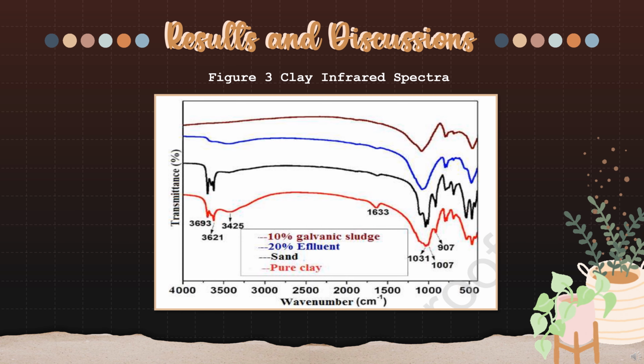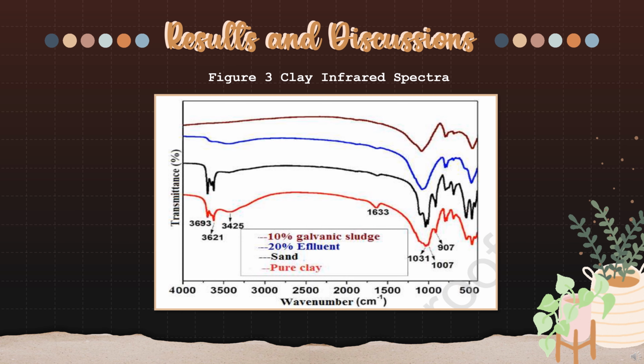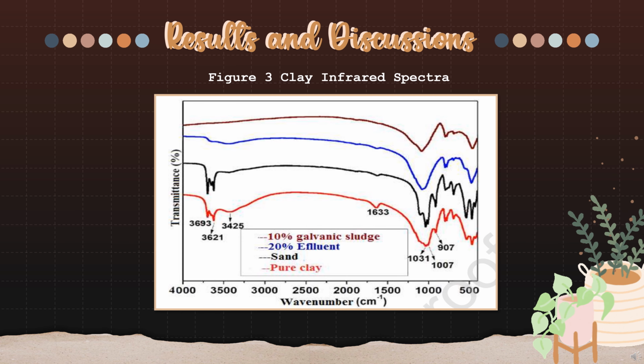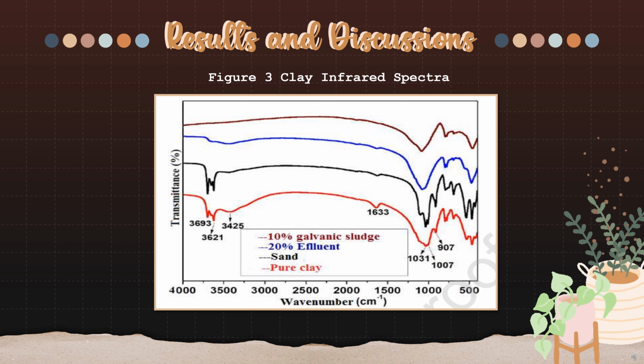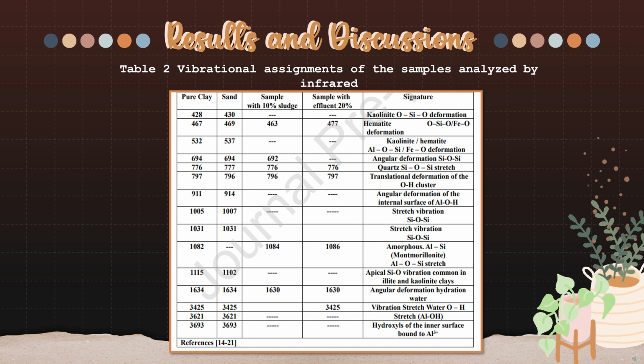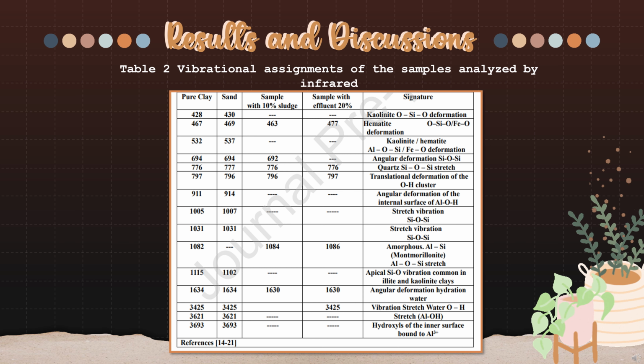Then the researchers discovered that the temperatures used to convert the sludge into a ceramic additive were insufficient to crystallize the substance. An endothermic reaction occurs between 400 and 600 degrees Celsius in which the crystalline structure of the clay mineral changes, resulting in the formation of a semi-crystalline metastable phase known as metakaolinite in the case of kaolinite. Table 2 shows all infrared bands as well as their designated assignments.